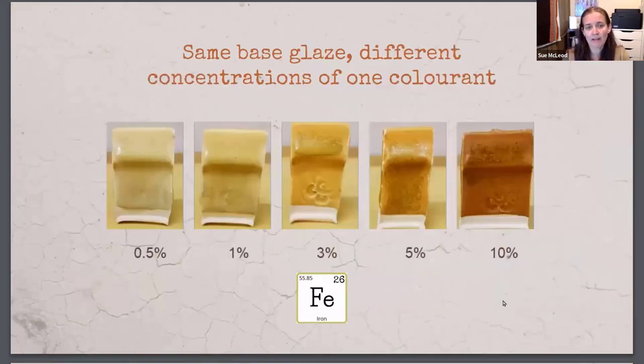This is an example of the same base glaze, but one colorant, different concentrations of one colorant. So these are all the same base glaze, but they have different percentages of iron. So you can see 0.5%, 1, 3, 5, and 10% iron. You can get anywhere from yellow to orange in this particular glaze when you increase the percentage of iron. So increasing the concentration of the colorant is another way to change the colors of your glazes.